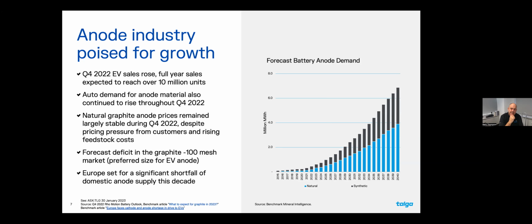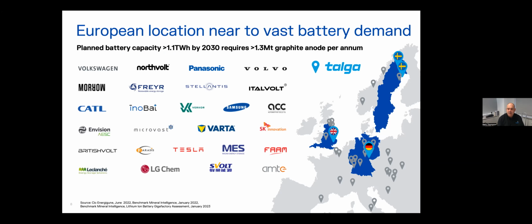And certainly there's a big deficit. You can look for Benchmark, look for Roskill, look for Fastmarkets data. They tend to cover a lot of that technical side of the industry. But there's a huge shortfall expected, including in Europe, where the planned battery capacity now exceeds 1 terawatt hour per annum. Within the next 7 years, it reaches that point, which will require over 1.3 million tonnes of graphite anode per annum. And that is in contrast to our stage 1 project, which makes only just under 20,000 tonnes per year, and an expanded Nunasvaara project does 100,000 tonnes per year.